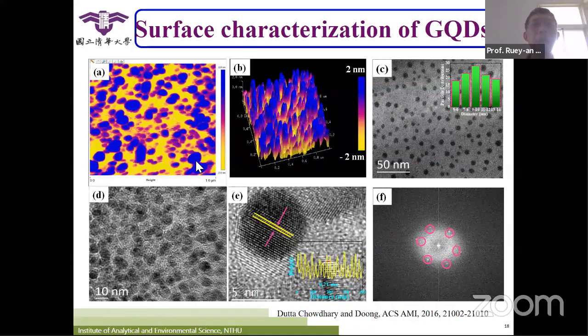So here is the case. When you see the blue colors, that's the graphene quantum dots. When you use the atomic force microscope to see the topography and measure the thickness of the carbon-based material, you can see their thickness is only around 2 nanometers. One layer of carbon is around 0.334 nanometers. Graphene oxide will be around 0.8 nanometer. So the 2 nanometers means they only have a few layers of carbon. Since there are only a few layers, we can make sure it's a graphene quantum dot and not a carbon dot. On figure C, we see their particle size from the TEM.